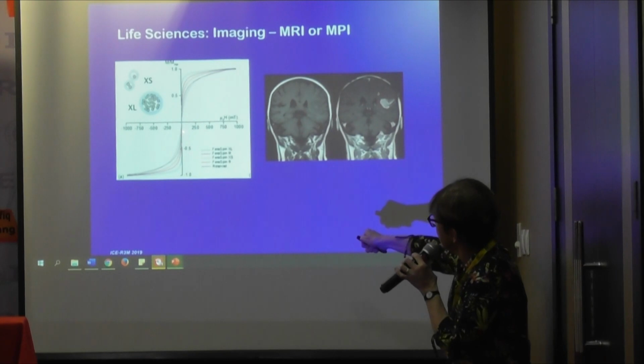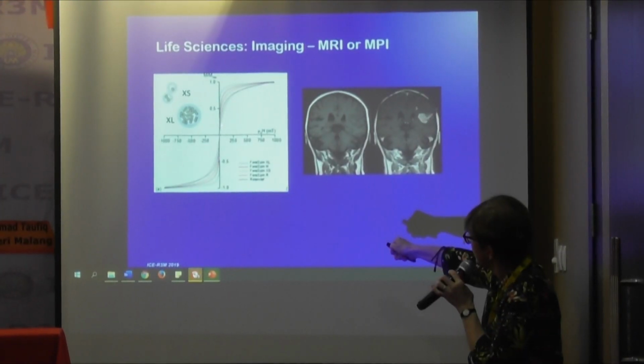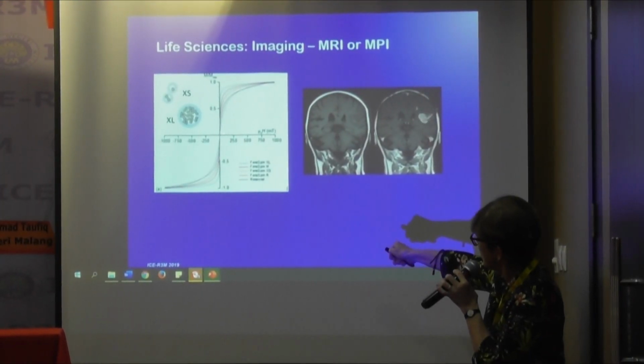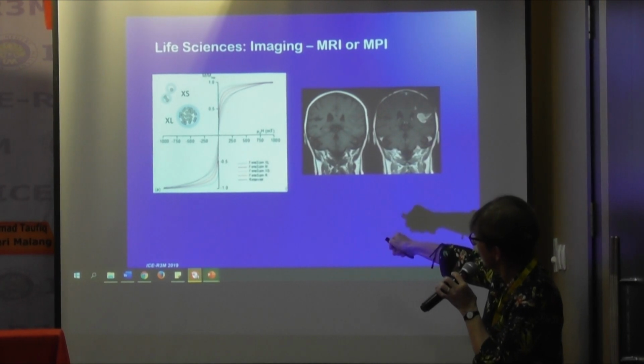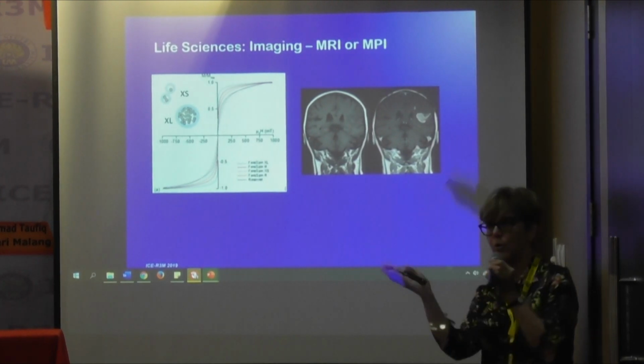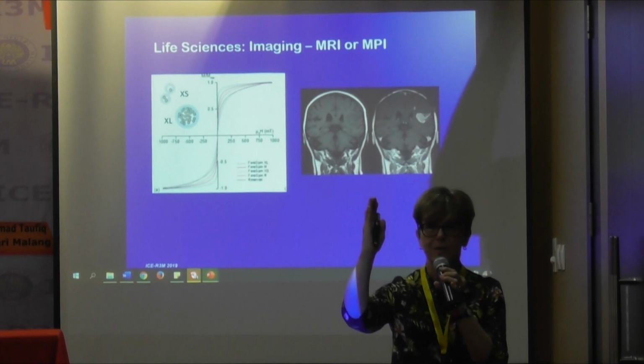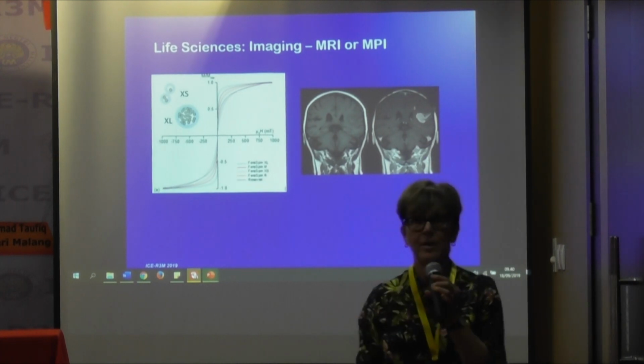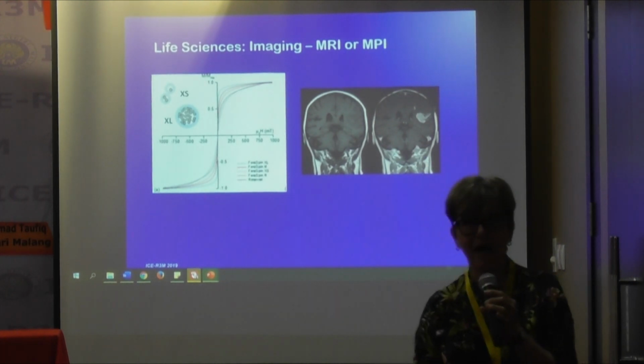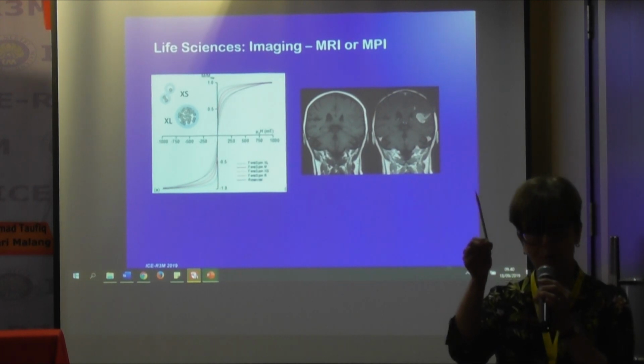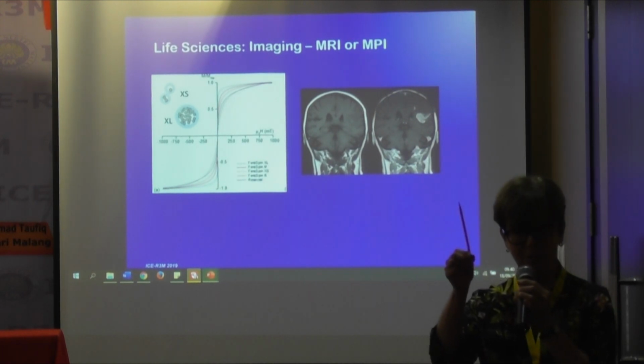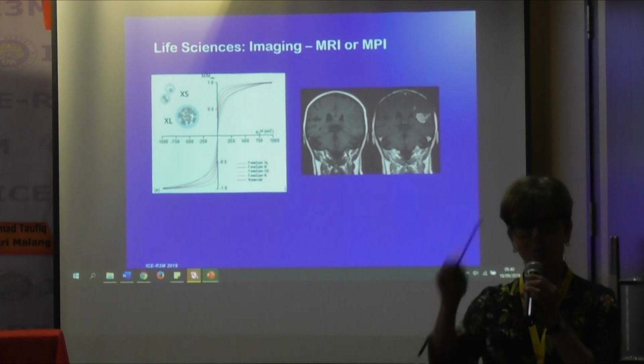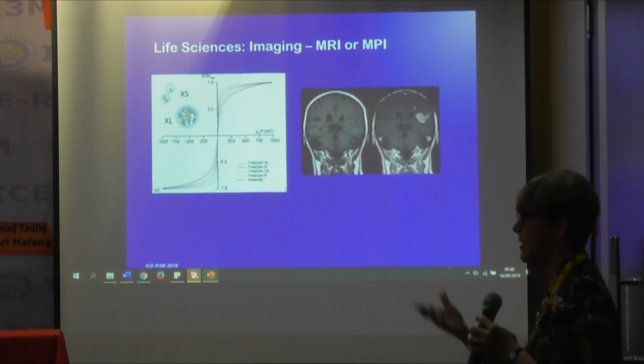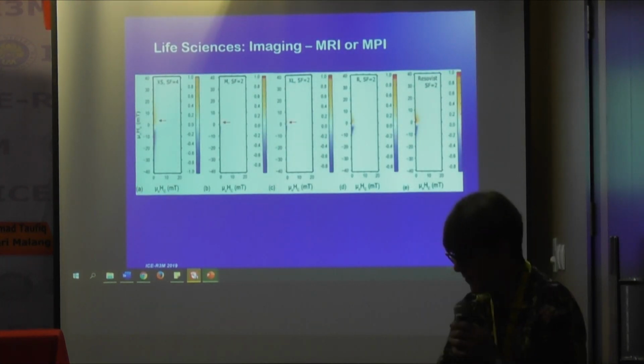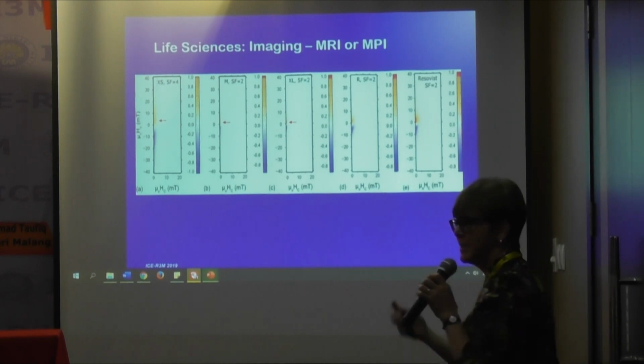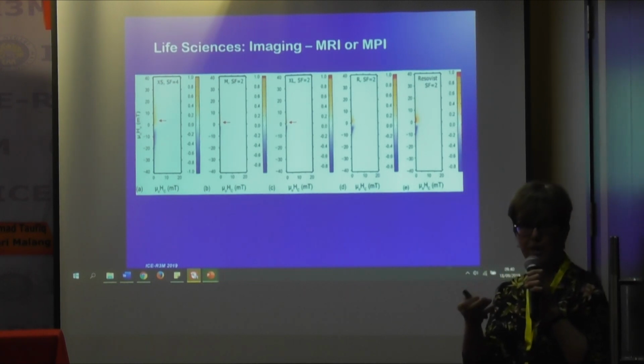And what you see is, if you go to the very small particles, the slope is lower than if you go to the very large particles. So the larger the particle, the steeper the hysteresis curve is, okay? And if you have a very high slope, that means you have a high susceptibility, which means it's going to react very easily to a field. Okay, next.